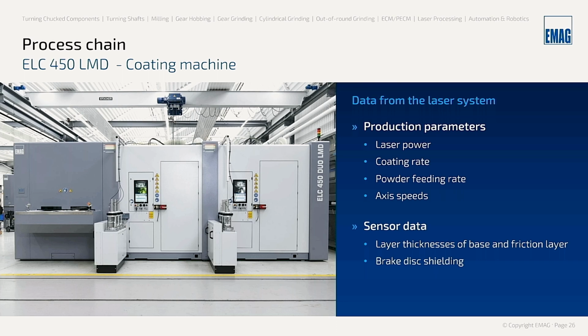Also, we collect the data from the coating machine. Here we normally collect production parameters like laser power, coating rate, the powder feeding rate, the axis speeds, or the temperature, and sensor data like the layer thickness sensor of the base and the friction layer, the brake disc shielding, or information from the melt pool monitoring.